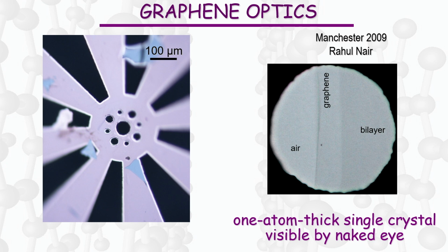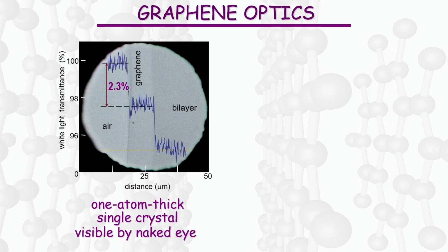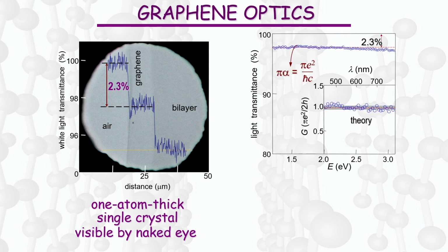that material is gray, so it absorbs some light, and access to this material allowed us to check how light is absorbed by it. This has been done essentially by analyzing the optical image. And what you find out is that each layer of graphene absorbs 2.3%. 2.3% seems to be a random number, but if you are a condensed matter physicist, you always use some analysis, and the analysis tells you that it's not a random number, it's pi multiplied by the fine structure constant.